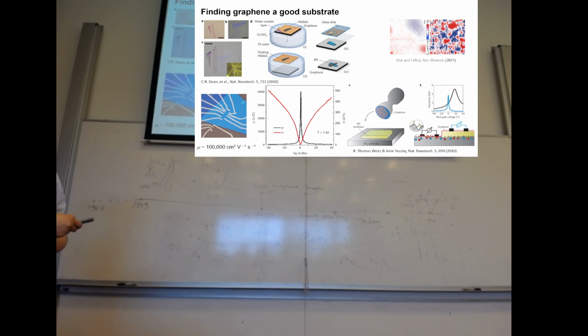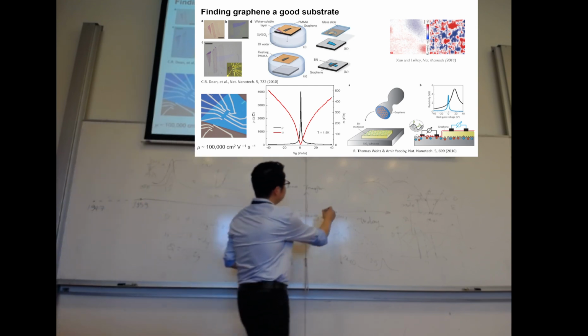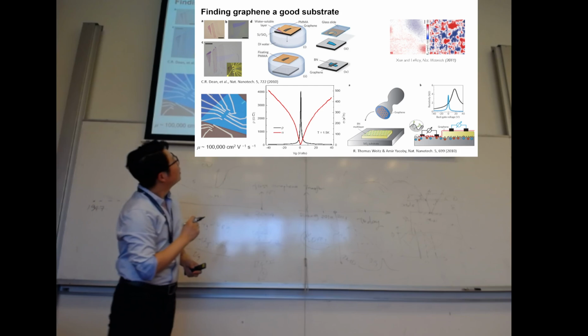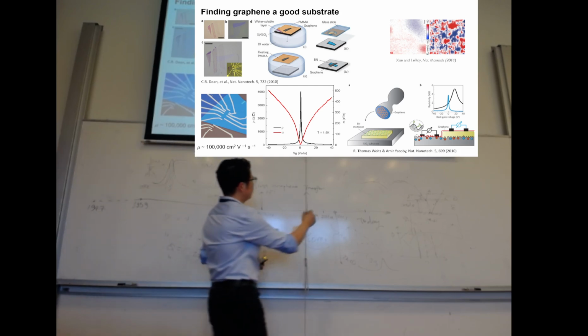Because on silicon oxide, graphene is lying on a rough surface with a lot of dangling bonds, and on hexagonal boron nitride it is atomically flat and clean, there's no dangling bond. So we have a very homogeneous spatial distribution of charges. So that's a big story at 2010. So we have to mark this one down here. I think it's 2010, yes.